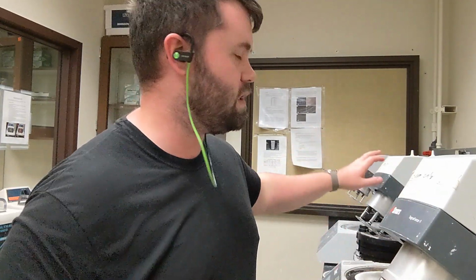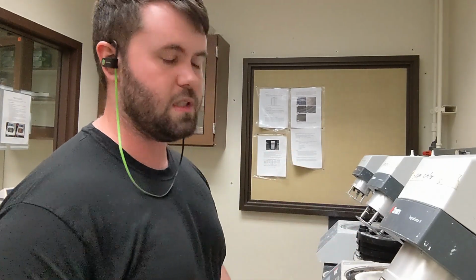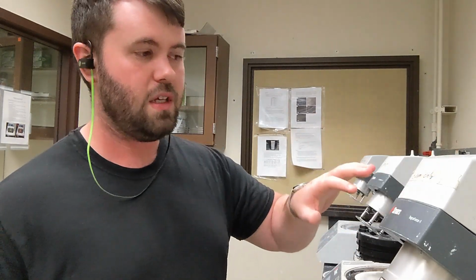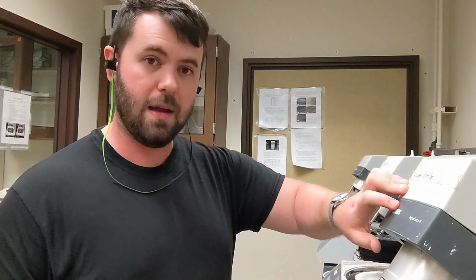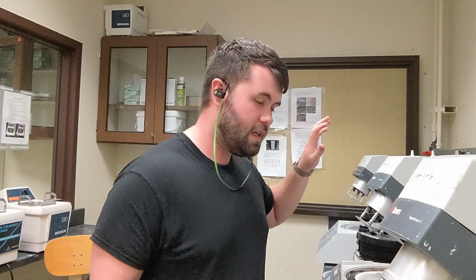And for each of these 3 machines, the diamond particles get progressively smaller. So again, this is similar to finer polishing steps. So our first machine, this one, uses 6 micron diameter particles. Second uses 1, and our third uses 0.3 micron or 300 nanometer size polishing particles. So the way these machines work,